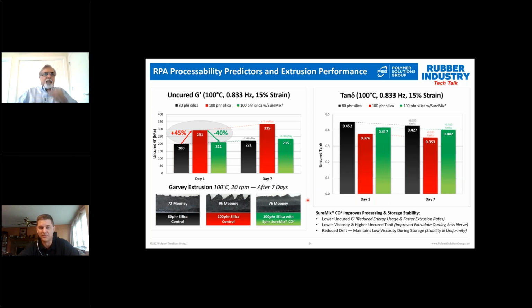very close to the 72 Mooney of the 80 part silica compound. So one thing that we always like to point out is also the uncured tangent delta. Uncured tangent delta, if you're not familiar with it, is a great tool to show you the processability of the compound with respect to how smooth the compound is going to extrude. All right, so the uncured G prime gives you viscosity, the tangent delta gives you smoothness of extrusion. And in this case, higher is better. And you see the improvement going from the red compound to the green by the inclusion of SureMix.